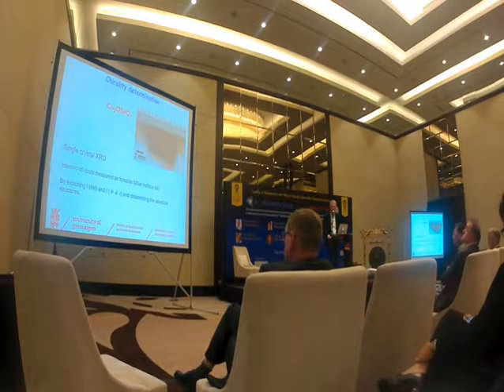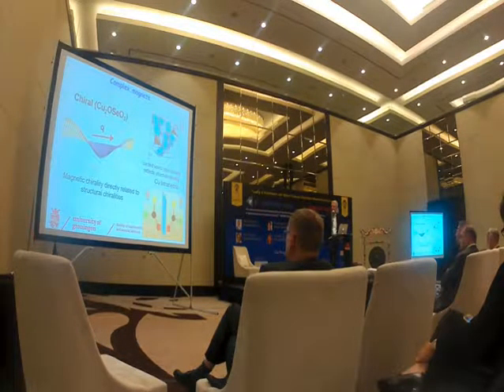This copper oxide selenide lacks inversion symmetry. This is the crystal structure, but if the crystal structure lacks inversion symmetry, so does also the magnetic structure. So if you have lack of inversion symmetry, also your spin structure lacks inversion symmetry, and in this case you get a chiral spin structure in your material. The chirality is the clue by which the magnetic information is being transported and processed.